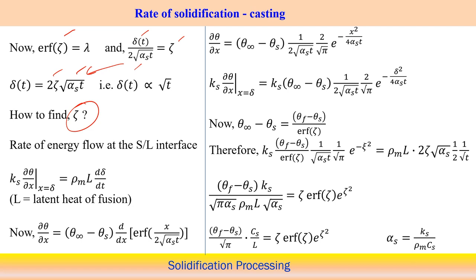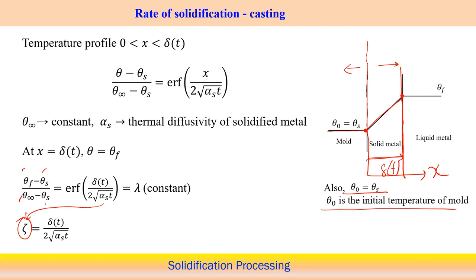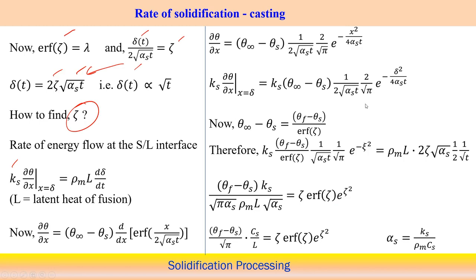Now, the rate of energy flow at the solid-liquid interface. We know the heat transfer q, if we apply the Fourier heat conduction law here also, heat flux equals k into dt by dx. So here k s into del theta by del x at x equal to delta. At this point, x equal to delta, what is the value of the temperature gradient del theta by del x? That we will try to find out on this surface, x equal to delta, and that should be equal to rho m, the density of the liquid metal, times the latent heat, and this is d delta, and how the delta value changes.